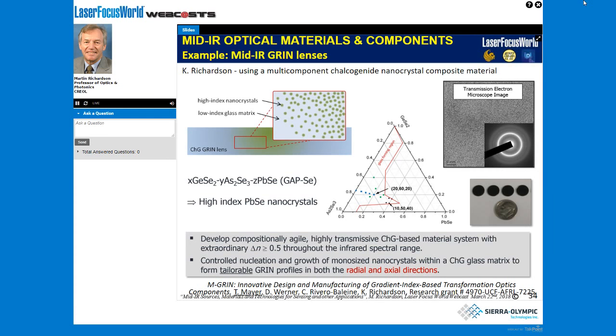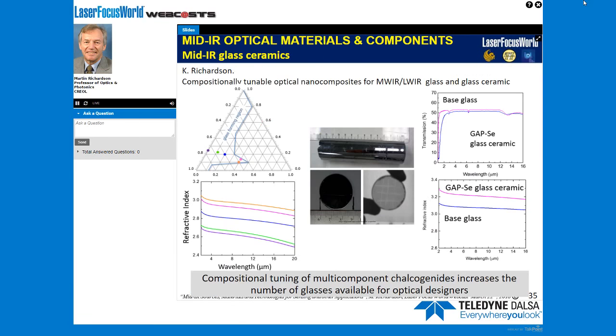for the experts in this field to start to think about using these materials as GRIN lenses, for instance, and GRIN lenses potentially will have applications in many mid-infrared systems. There's a couple of examples here of these GRIN lenses and GRIN materials. You can also see that these materials have very high transmission across broad regions of the mid-IR, stretching from 2 microns out to 16 microns. And a comparison of these GAP-Se materials with the base glass of GAP-Se without the nanoparticles in. And you can see how on the left-hand side you can get very precise control of the refractive index across these wavelength regions by using these glass ceramics.